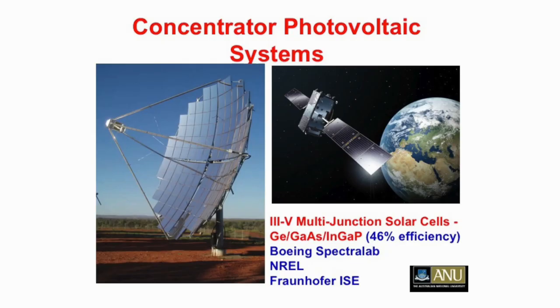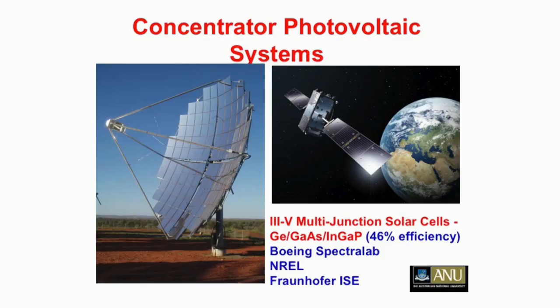So solar cells. Already people have developed solar cells using the materials which we work on at about 46% efficiency. Your rooftop solar cells may be about 15% or 20% efficient, and people have already developed 46% efficient solar cells. So the only problem is they're expensive. So where can we use these solar cells? And of course, space applications. In fact, these solar cells have been developed for space applications by Boeing, the National Renewable Energy Laboratory in the US, and Fraunhofer in Germany or so. So by stacking different materials, you can get very high performance solar cells.